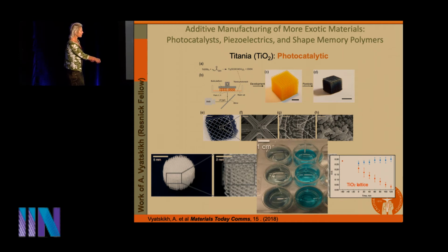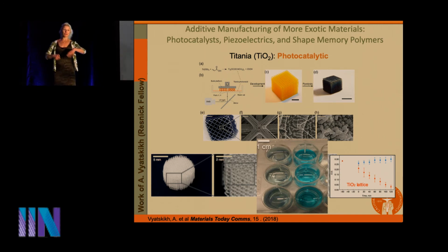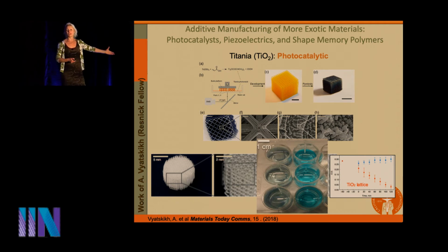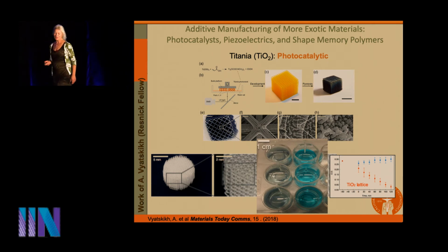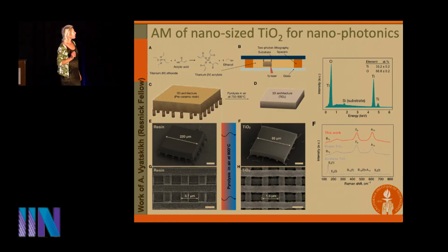And you can see that with time, it deactivates it. So this blue color turns into clear with the presence of this titania lattice. So you can imagine inserting these into water bottles, which are full of E. coli or other harmful bacteria, exposing it to sunlight, and voila, you have your water purified. And the advantage here is that the titania scaffold is not in the form factor of nanoparticles, which you can't extract out of the water. This you can just lift out of your bottle, and so you don't have to drink the titania as well. So here's one example. Now, titania also has nanophotonic properties.